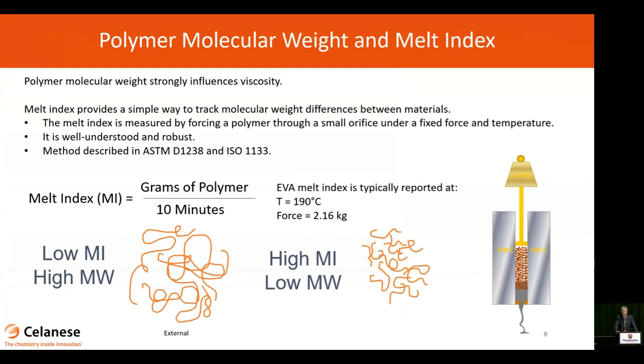So the first thing you want to characterize with the polymer is the molecular weight. And we'll talk more about using things like gel permeation chromatography in a minute. But actually, the method that's typically used to do product release and product specification for a material like this is something different. It's a melt index. So this is done for a variety of reasons, but not the least of which is it's a very fast, reproducible, robust method. So what you're doing is you're taking advantage of the fact that as a polymer molecular weight increases, its viscosity also will increase, right?